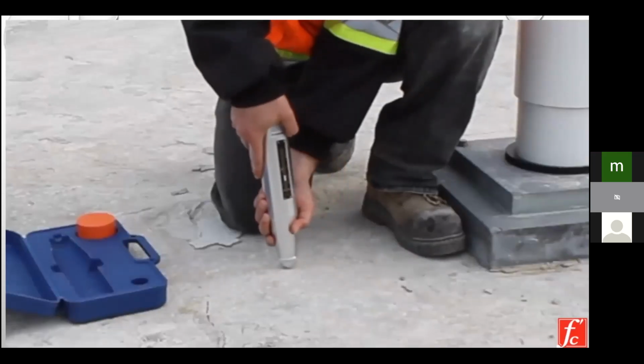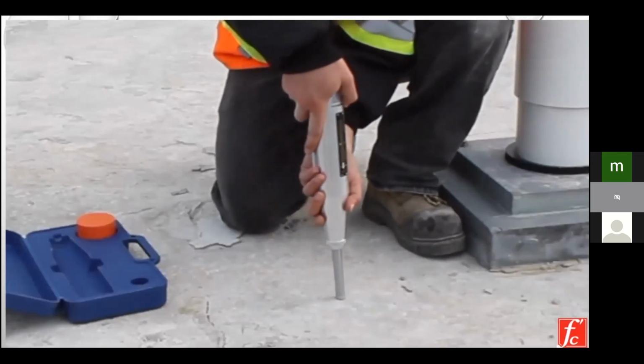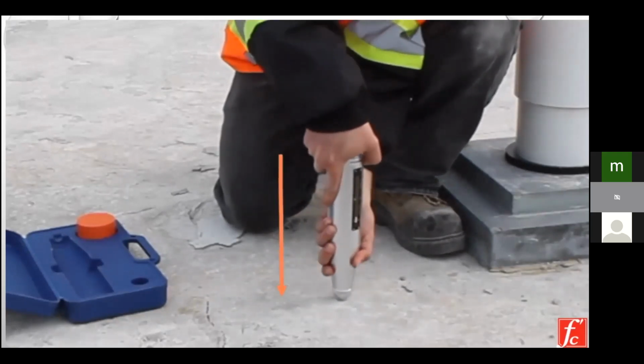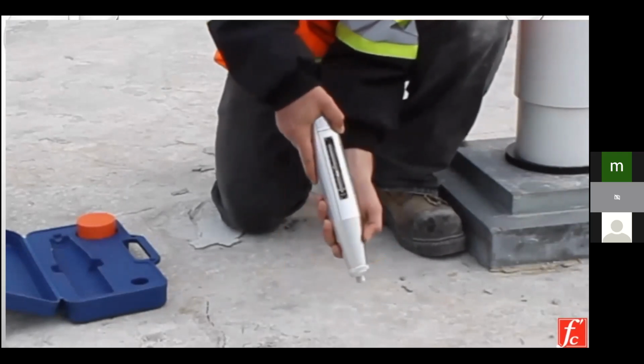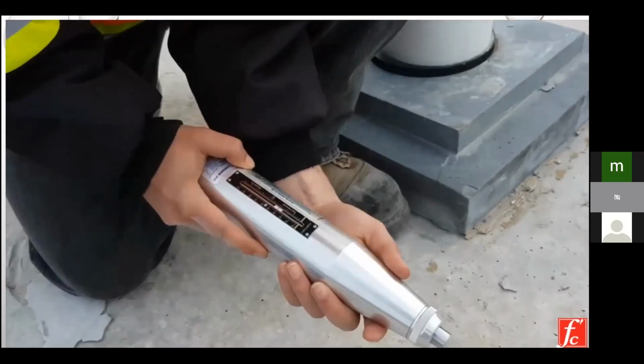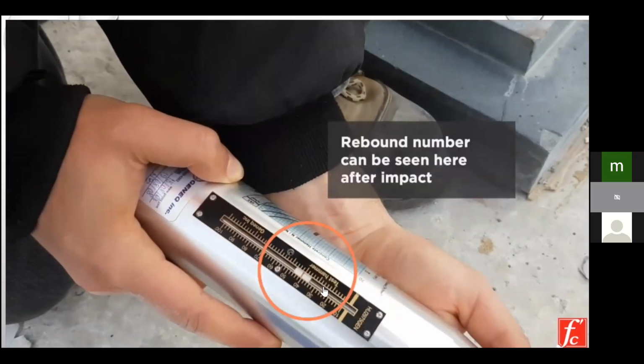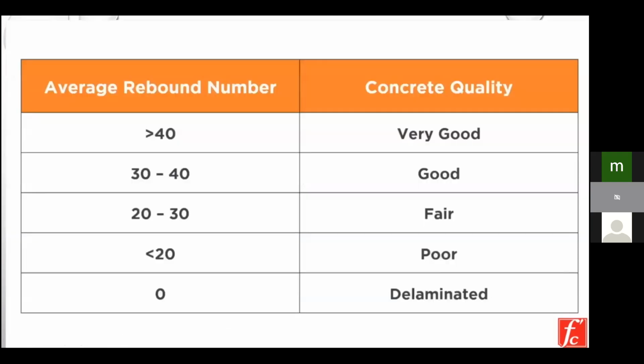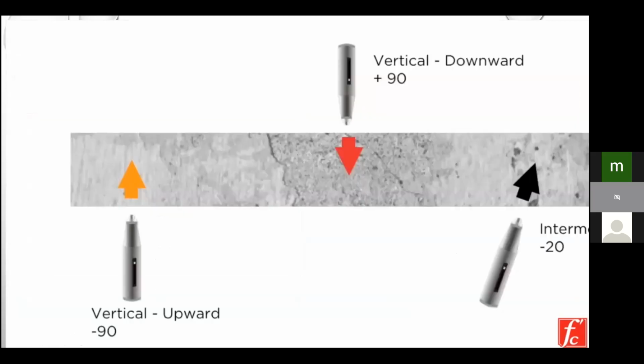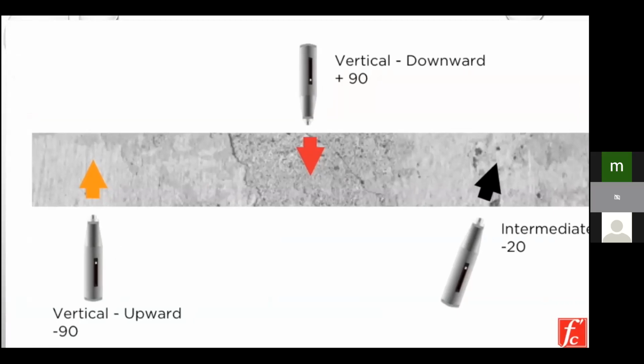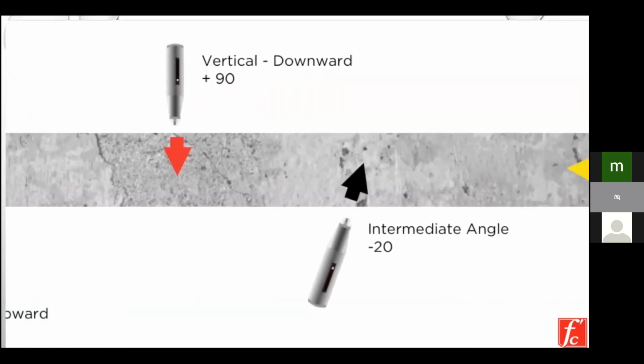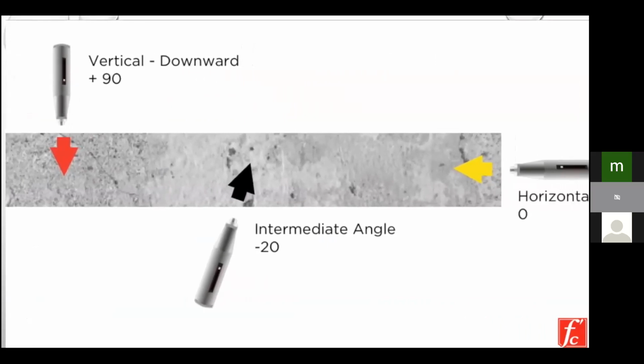In order to test, the plunger is pushed against the concrete perpendicular to the surface. As the hammer body is pushed towards the concrete, the force causes the latch to release and make an impact on the concrete. Essentially, the rebound of the spring-driven mass is measured after its impact with concrete surfaces. The output of the rebound hammer is then referred to as the rebound number, and this is correlated with the surface hardness of concrete. A higher R number means higher concrete hardness. The rebound hammer can be placed in many configurations, including upwards, downwards, at any intermediate angle, and horizontal.